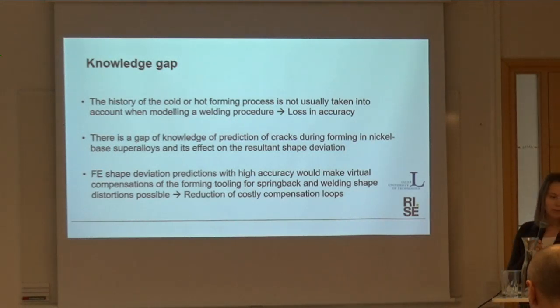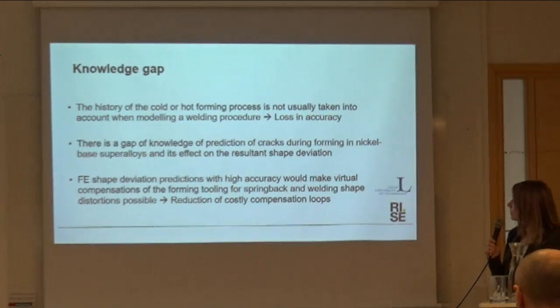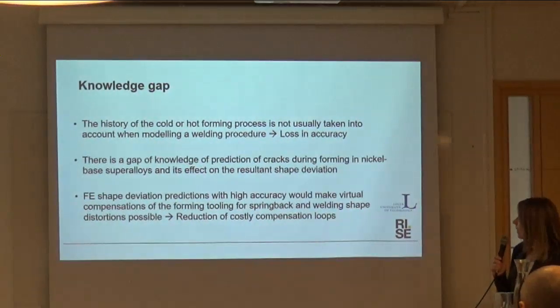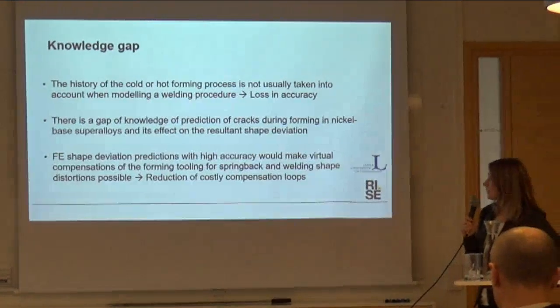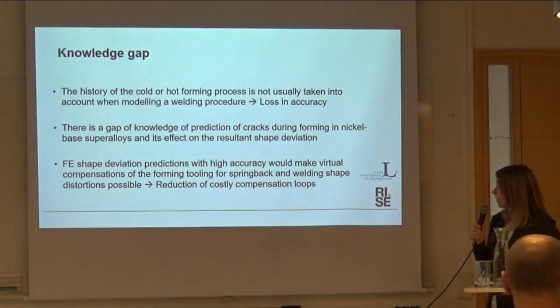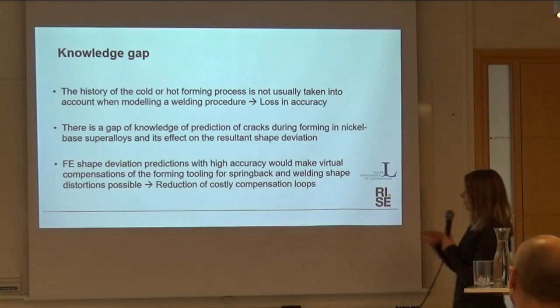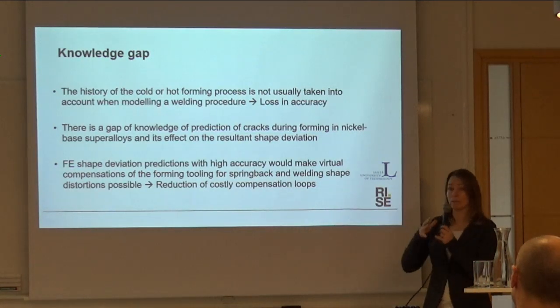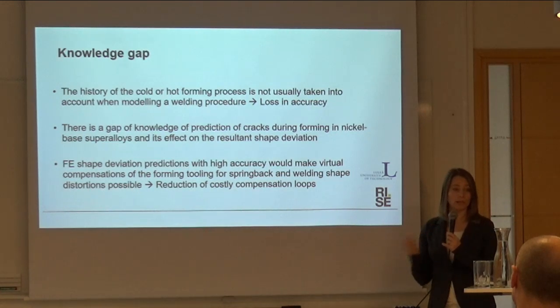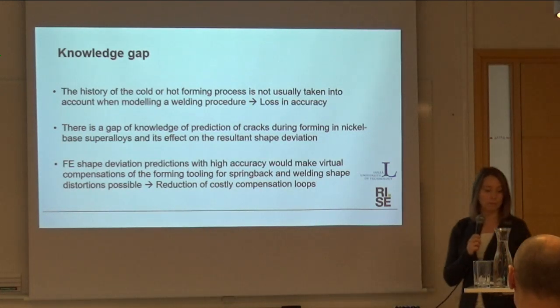There is also a gap of knowledge when it comes to predicting cracks during forming in these materials. And if we can have high accuracy in these simulations, as I mentioned, we can also compensate the forming tooling not only for the spring back after forming but also for welding deformations. So I will give some examples here.